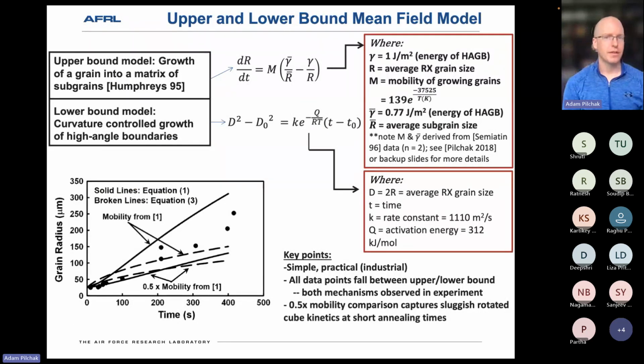So as I mentioned, there were two competing mechanisms happening here. We had these fine recrystallized nuclei growing into a matrix of subgrains, and obviously the recrystallized nuclei are relatively clean, dislocation free, but they're surrounded by this matrix of subgrains. And of course, what makes up the subgrain boundaries are arrays of dislocations. Dislocations add energy to the system, so it's advantageous for the overall strain energy of the system for those recrystallized nuclei to grow and consume some of those subgrain boundaries, and that actually leads to a faster growth rate as compared to, say, curvature controlled grain boundary motion.